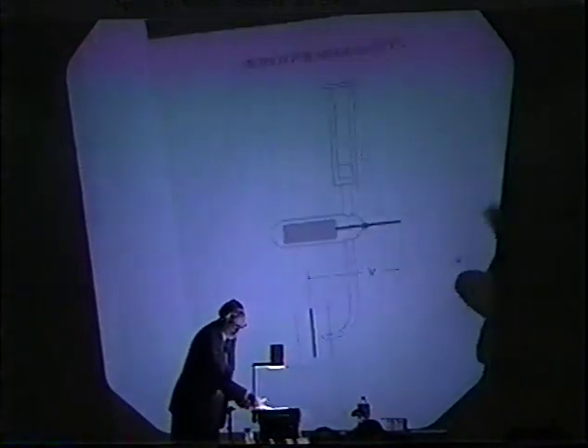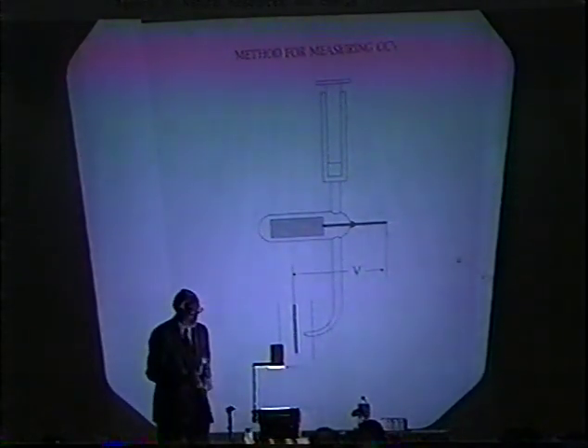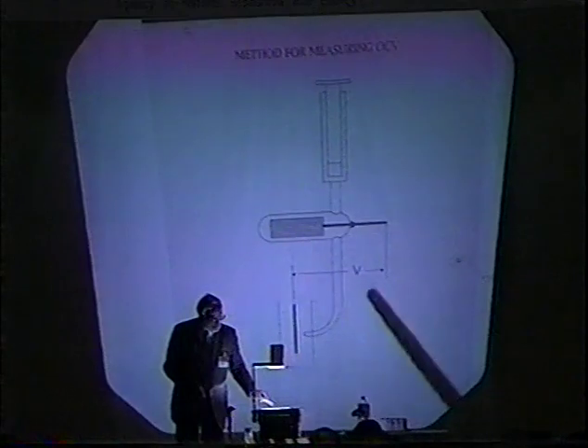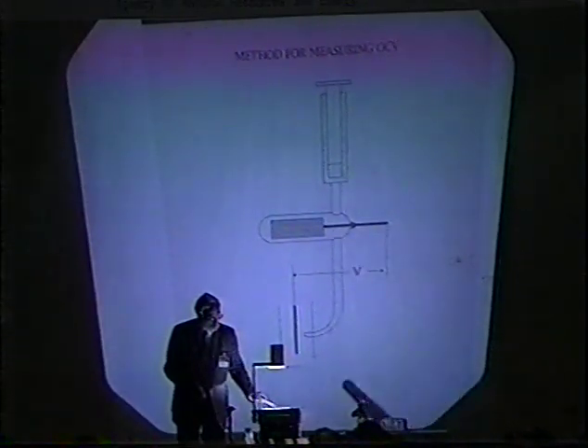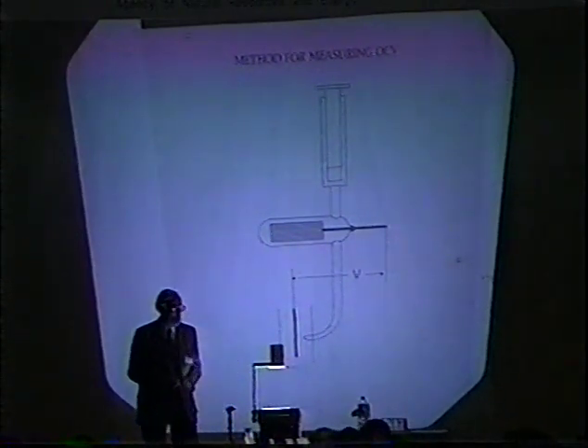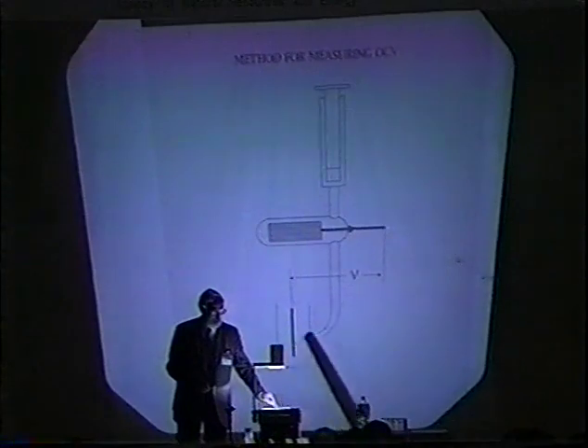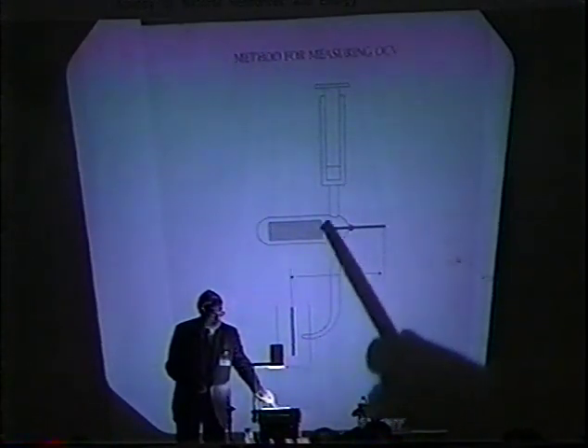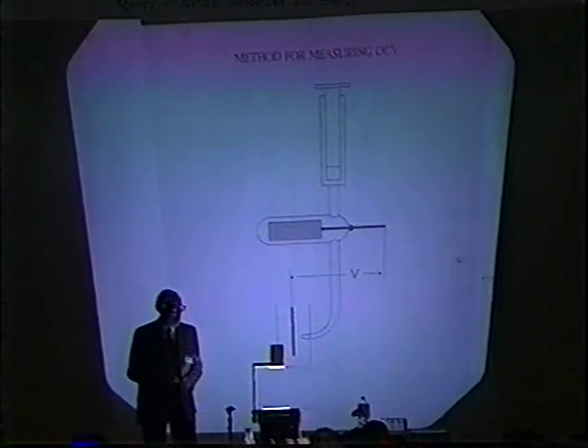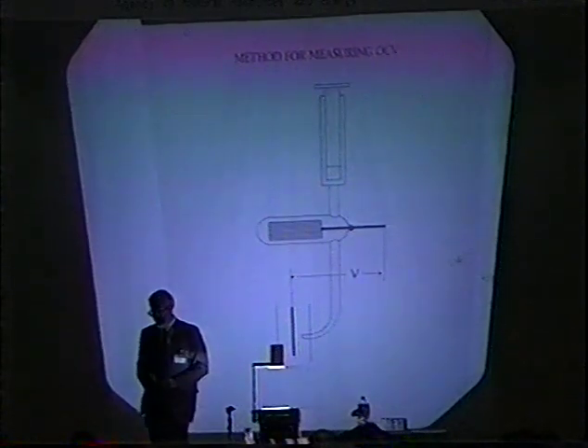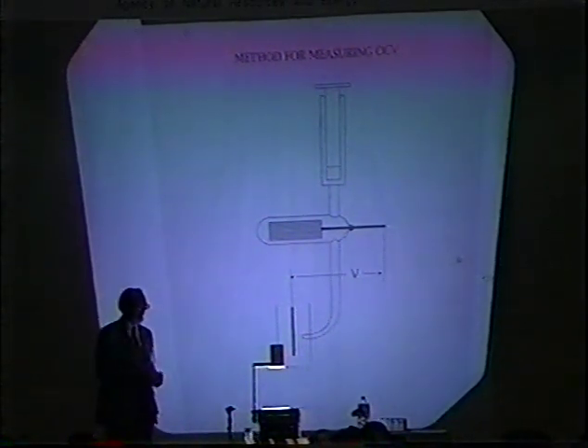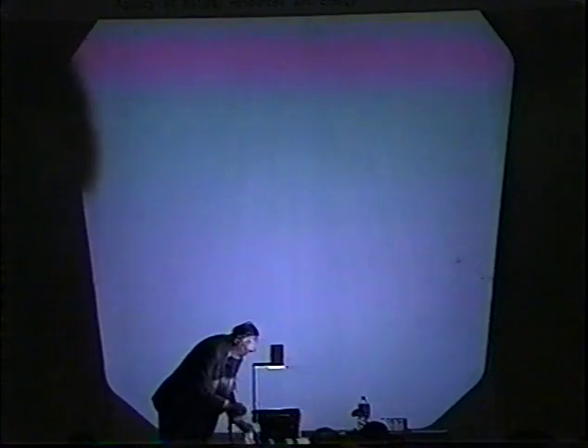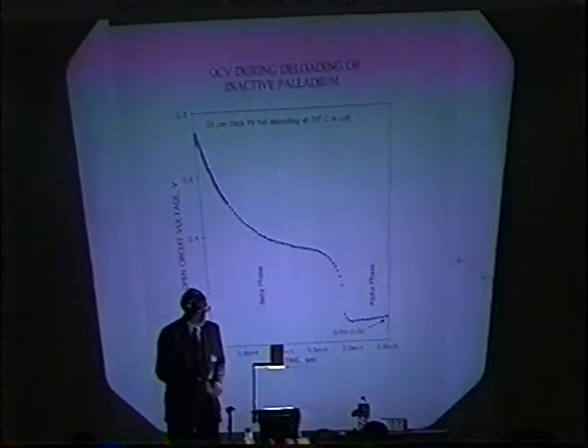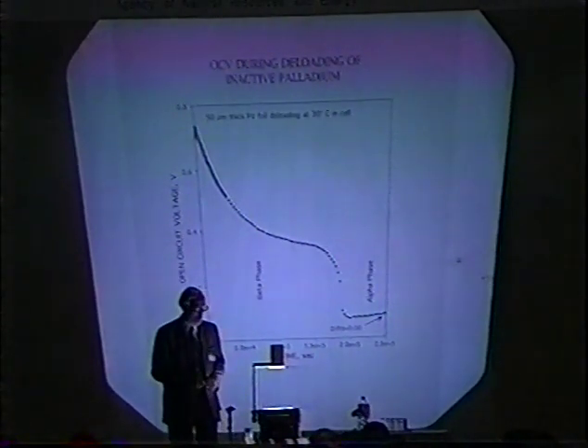So let's look at the open circuit voltage. That's one of the very interesting measurements we can make. It's determined by measuring the voltage between a platinum reference electrode and the cathode during a time when there's no current flowing between the anode and cathode in the cell. This tube is filled with electrolyte and that provides the conductive bridge. The platinum reference to pure palladium has essentially maybe 20 millivolts difference. But when the palladium is loaded with deuterium, the voltage goes up to quite reasonably high values.